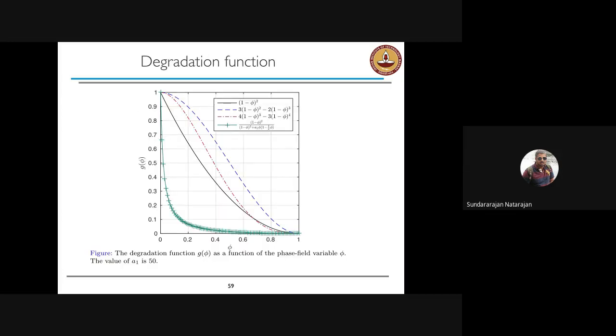There are different degradation functions that are used in the literature, and this dictates how fast you go from an undamaged to a damaged state. There are quadratic variations, and there are more complex forms. The simplest one to implement would be the quadratic form, which is shown as a black line. So it takes a value of 1 at the crack tip, and it eventually goes to 0 away from the crack.